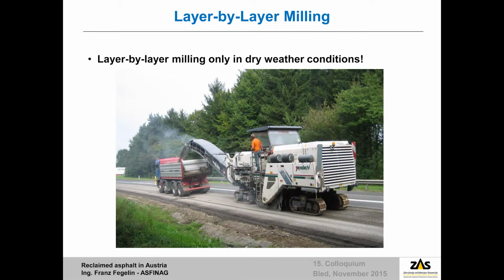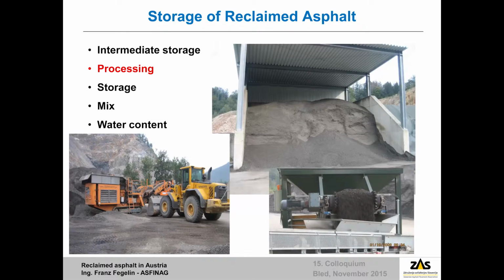As I told before, the first step is milling the raw material layer by layer as dry as possible. The depositing has to be carried out in such a way that each layer can be stored under covering in order to keep the water content as low as possible. Using this method, we got a water content not exceeding 3 to 5%, which is necessary for a good quality and also for the process in a mixing plant. Because with too high a water content, you would risk damages in the facilities because of explosions by steam.